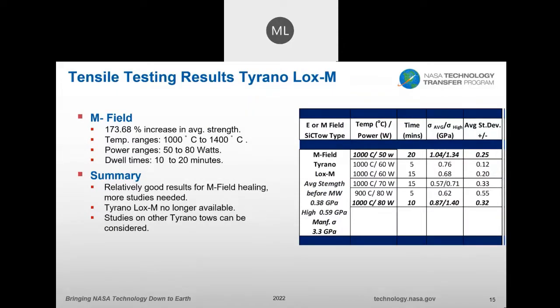In the case of Lox-M results, we didn't have a lot of fiber, and this fiber is really not produced anymore. But we're going to take a look at what we did see. We had a 173% increase over the average strength that we measured. The temperature range from 1000 to 1400 degrees. Power ranges from 50 to 80 watts, and dwell times between 10 and 20 minutes to see any effects.